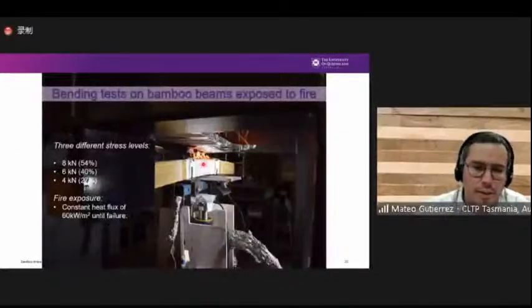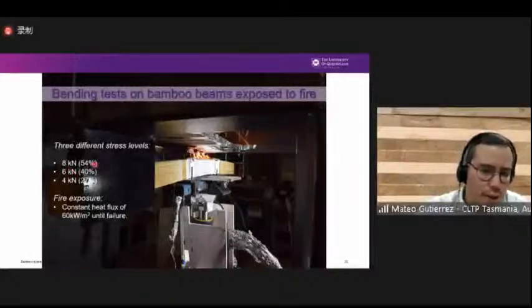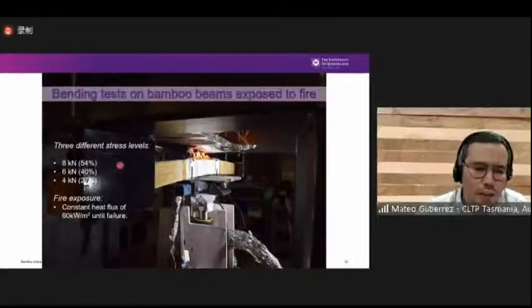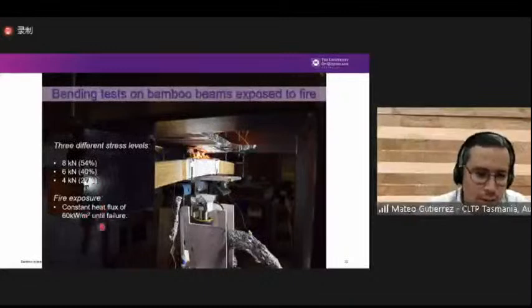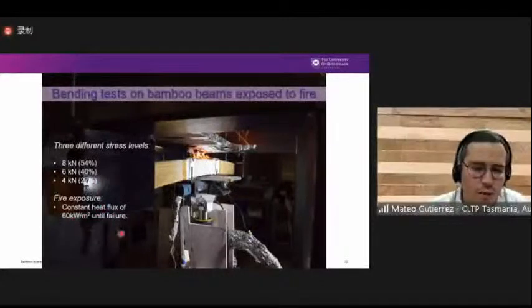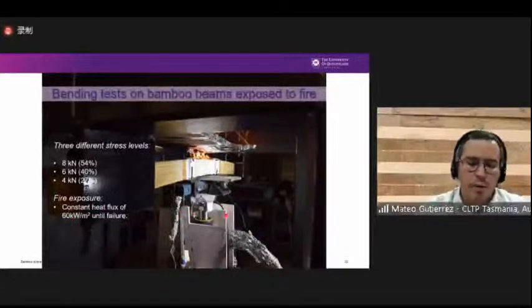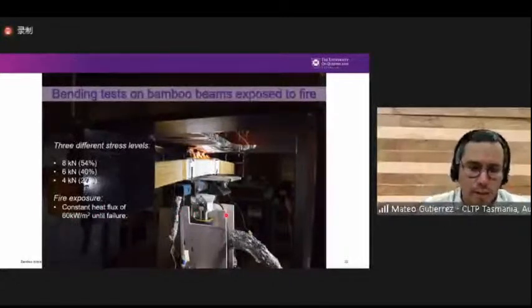And then we said, okay, in order to test the beams with fire exposure, if the failure load was 15 kilonewtons, let's do some tests at 8 kilonewtons, at 6 kilonewtons, and at 4 kilonewtons, which will be equivalent to 54% of the failure load, 40% of the failure load, and 27% of the failure load. All the beams were exposed to, again, constant incident heat flux of 60 kilowatts per square meter. And basically what we were doing was to load the beam until we reach the target load, and then we start burning the beam until reaching the failure.